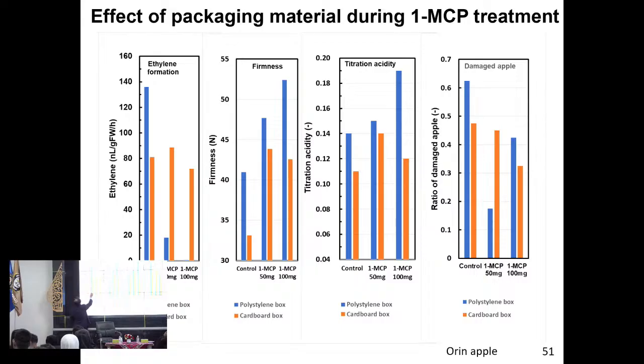And then this is the formation already occurring. When we use 1-MCP at 50 milligrams, 100 milligrams, we can almost stop the ethylene formation.